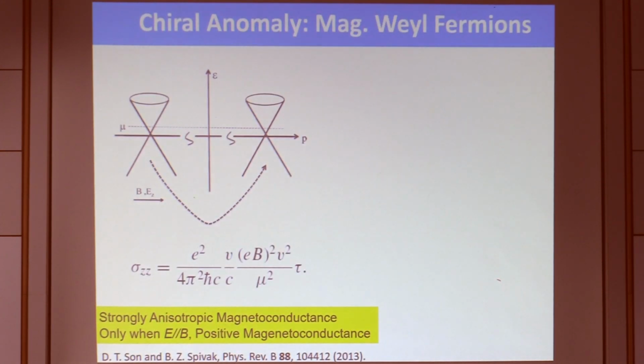Another test to verify whether there is any Weyl fermion near the Fermi energy is to use the chiral anomaly. This is actually a high energy physics concept, which tells us that if you have two Weyl points, because these are linearly propagating fermions, there is a conservation law for each Weyl fermion. But in reality, when you apply a field along the electric field, this conservation law breaks down, and there must be a huge drop of the magnetoresistivity or a huge increase of the magnetoconductivity.